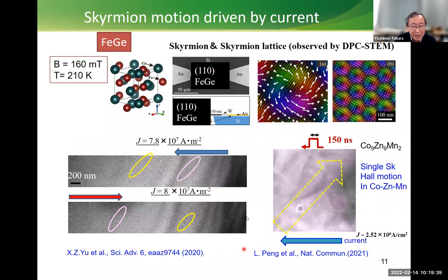We showed some examples. This uses iron germanide, a typical B20 chiral magnet. You see the skyrmions originally here. The three skyrmions you can see, and the current flows here. So the electron flow is along this direction. Then this skyrmion moved to here. Importantly, only 60 or 70 nanometer skyrmions, very narrow scale skyrmions, can be visualized, and its motion is captured. But if you apply the current flow in a different direction, then the skyrmion moves from here to here.